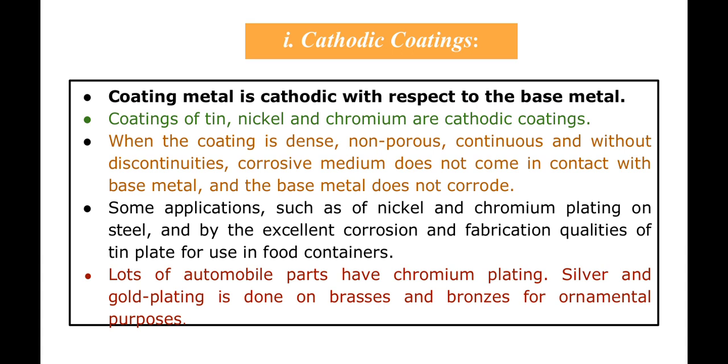Coating being cathodic does not corrode. Okay, so corrosion of the underlying metal occurs at small discontinuities, cracks, etc. And as it is anodic, as the anodic area is small, pitting corrosion will occur, and this disadvantage is overlooked for some applications where corrosion is not a severe problem.